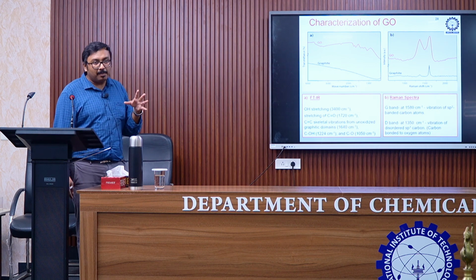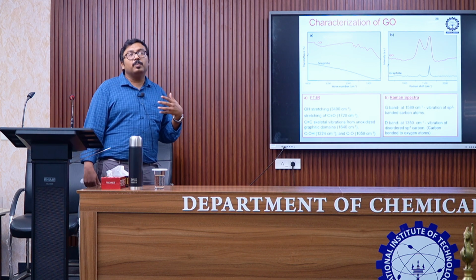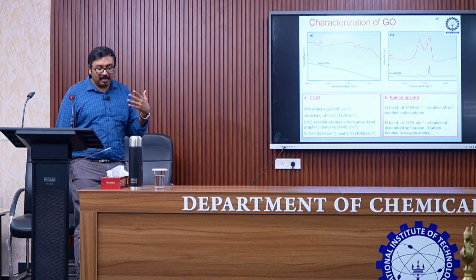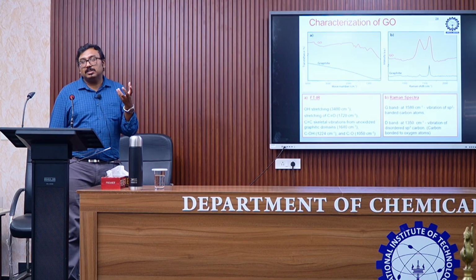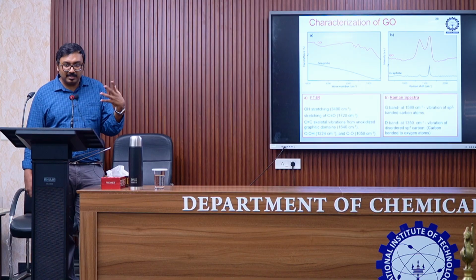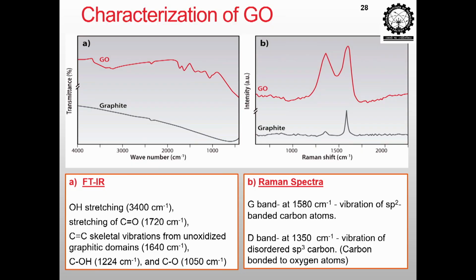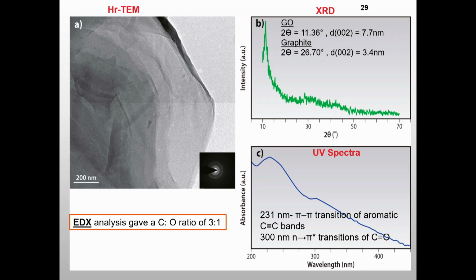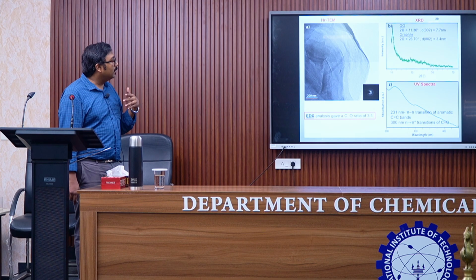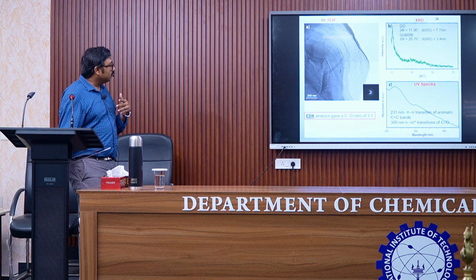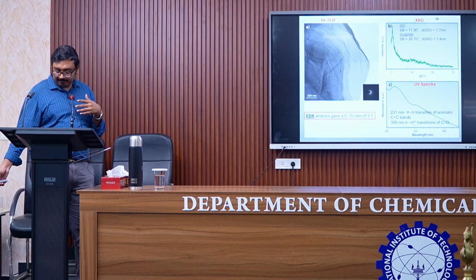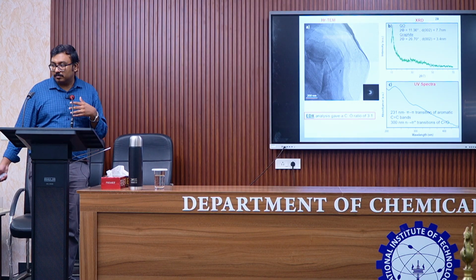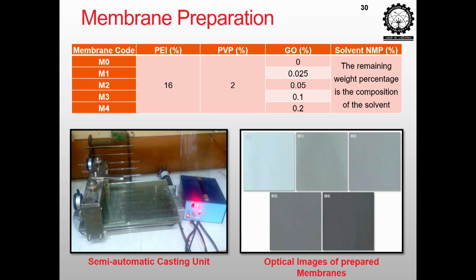Graphene as such is carbon that has no functional groups, but we need it in its oxide form because it gives the OH, COOH or epoxy oxygens that would increase the hydrophilic character of the membranes. They were again evaluated by TEM, XRD, UV spectra where we could find the band gap and 2 theta, etc. Then these were used to prepare the polyetherimide membrane.